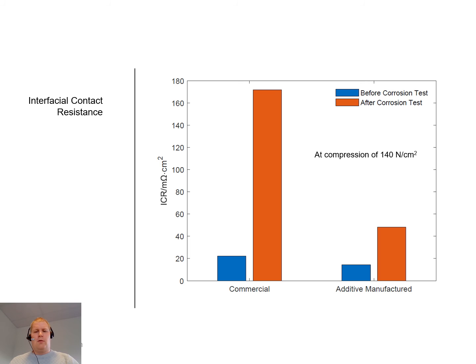A pressure of 140 Newton per square centimeter was applied on the samples. This is due to reports in the literature that this value is common for PEM fuel cell stacks. As you can clearly see, the ICR value for the commercial sample is higher than the additive manufactured sample, especially after the corrosion test. This indicates the formation of a more stable and maybe thicker protective layer on the commercial sample, protecting it more against corrosion, which we could clearly see in the previous results.